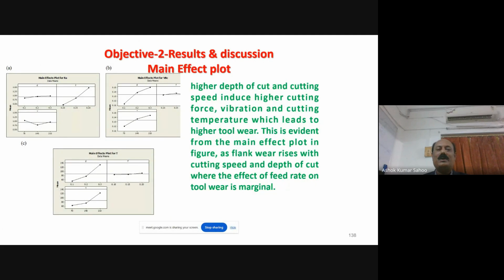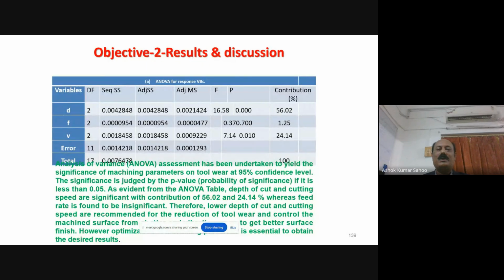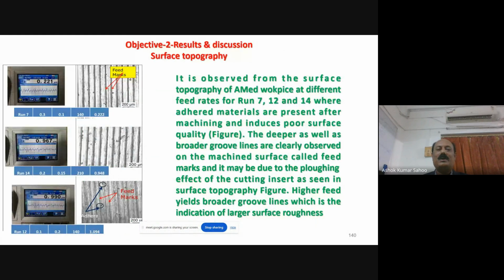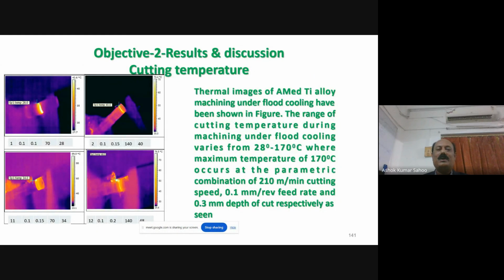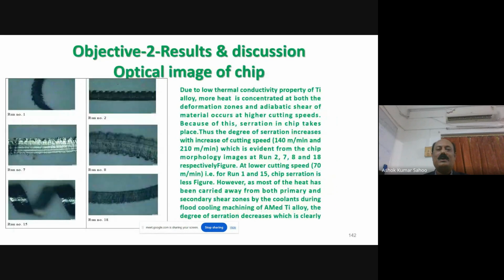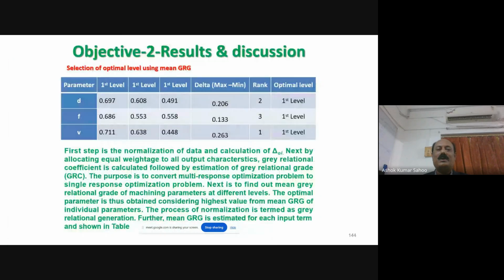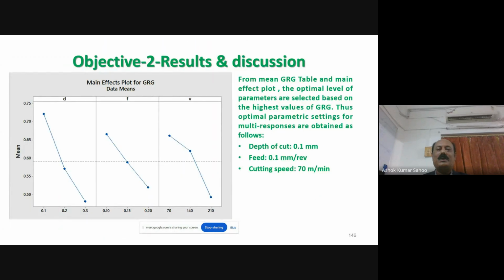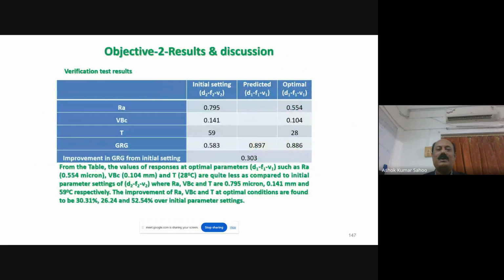Similarly, the parametric influences have been studied for the additive manufactured titanium alloy. Depth of cut and cutting speed are the most influencing parameters. As per ANOVA, surface quality is very good. Cutting temperature generated is within 28 to 170 degrees C. Sawtooth chips are also obtained. Optimize the process parameter: level 1 cutting speed, level 1 feed, and level 1 depth of cut are the optimal process parameters through Grey relational analysis.